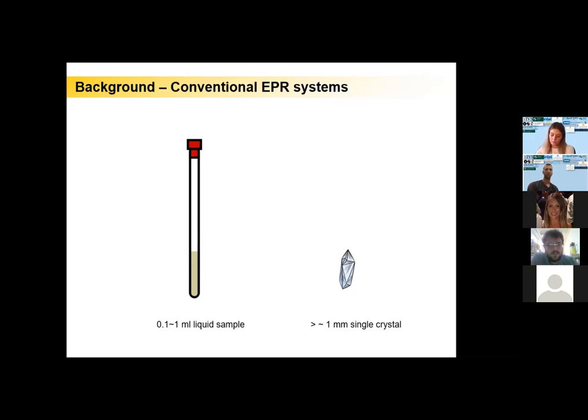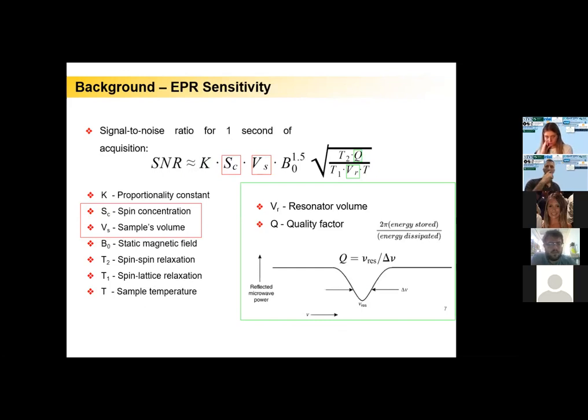So in our lab, this is what we did. I'm going to tell you the basic principles. This formula says that the signal to noise ratio depends on these parameters. So if we have some sample that has a limited spin concentration and limited volume, we can't make the sample smaller, but we can increase the sensitivity of our system. And we do that by increasing the quality factor of our resonators and decreasing the size of the resonator. We don't actually have to decrease the actual size of the resonator, but just the effective place where the magnetic field is concentrated.